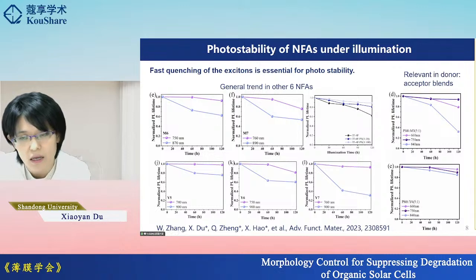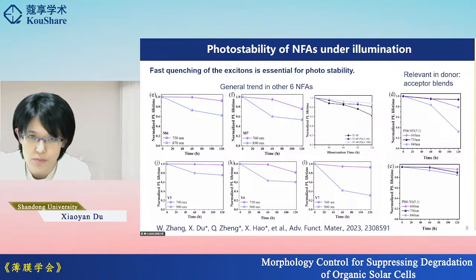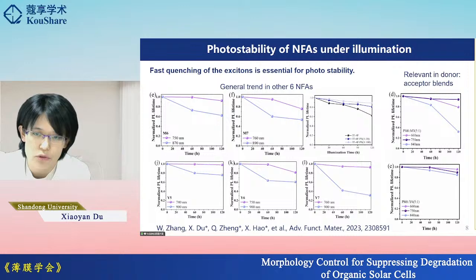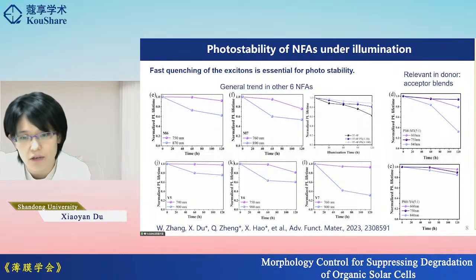think that the way to overcome this issue is to quickly quench excitons in the donor-acceptor components in the blend films. So fast quenching of excitons is not only important for the device performance, but also crucial for the photostability of these non-fullerene acceptors.